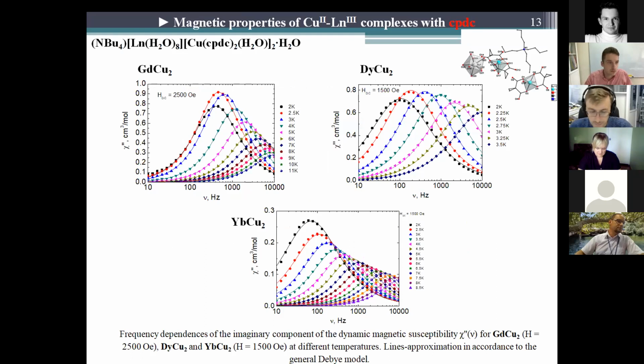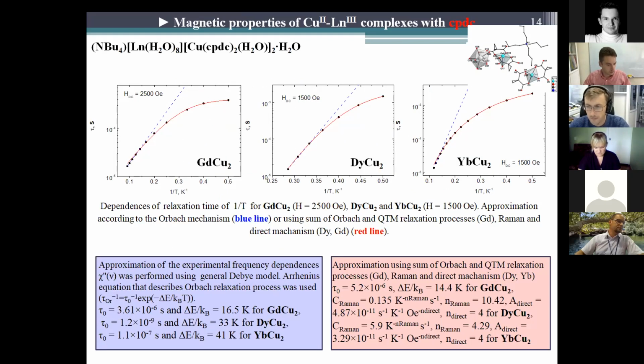In order to investigate the relaxation of magnetization of the obtained copper-lanthanide compounds and to understand whether they are single molecular magnets or not, we measured the magnetic susceptibility in the dynamic mode. The approximation of the obtained frequency dependencies of the imaginary component of the dynamic magnetic susceptibility using the generalized Debye model made it possible to estimate relaxation times. The pre-exponential factor and the value of the energy barrier of magnetization were determined.